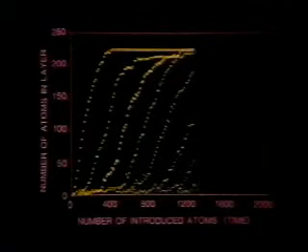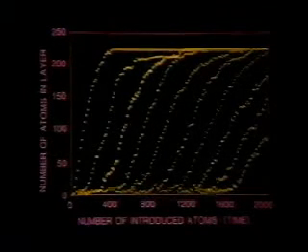A monoatomic metal cannot be grown amorphous even at the lowest temperatures. The growth is into defected polycrystalline material. Now imagine the surface of a metal, copper for example, at room temperature. One might expect a quite static surface, but the finding is amazing. The atomic mobility is quite high, giving rise to a high level of activity. Because of this high mobility, the layers become completed, the reason for the high temperature needed for good epitaxy.